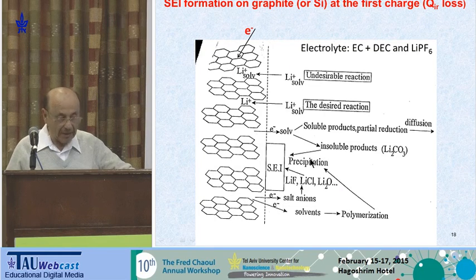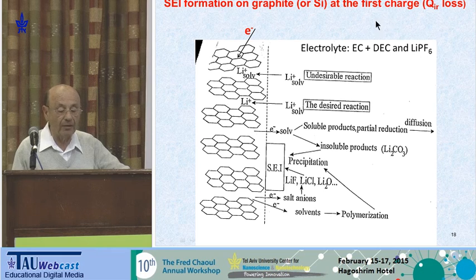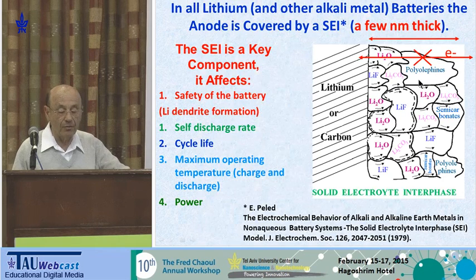And what happened is that I said lithium-ion batteries are assembled in the discharge state. The first step is to charge the battery, and you have graphite or silicon. You push electrons from the cathode into the anode, and this comes into the solution and reduces all the solution components, which are solvent and salt, and you have a precipitation of solid electrolyte particles. And you see what happened here.